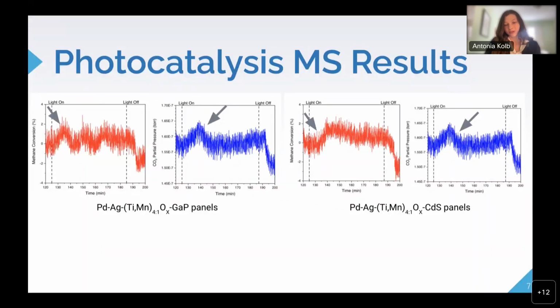Here was the mass spectroscopy data from the photoreactor from the experiments. The maximum methane conversion of both cadmium sulfide and gallium phosphide panels was around 2% methane conversion, with an increase in carbon dioxide concentrations in blue and methane conversion in red simultaneously, with reaction before and after the light was turned off, evidence of photocatalysis.